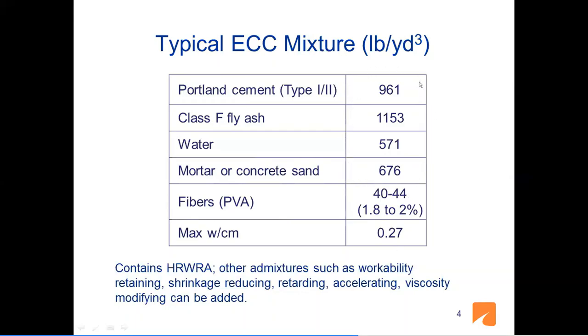As you see in these mixture proportions, it is a very rich mix, and such rich mixes are prone to shrinkage. I'll show you some shrinkage values later. It contains high-range water-reducing admixture to make it workable. In fact, it's a self-consolidating concrete. Other admixtures are also used, and workability retaining, shrinkage reducing, retarding, accelerating, and viscosity modifying admixtures can also be added.